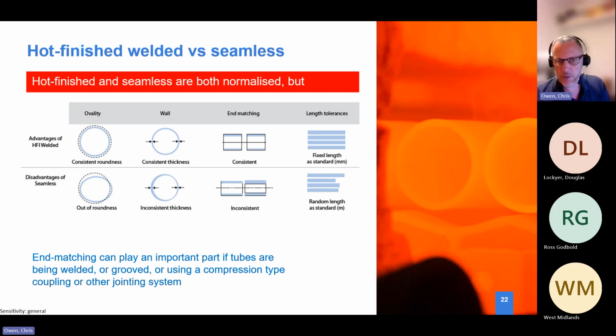And when we talk a bit later about corrosion issues and installation issues, it's worth noting that sometimes if you have seamless tube which has different end matchings, when they're welded together or joined together, there could actually be some steps internally, and that could act as an initiation point for corrosion or a place where debris can collect. So again, we will always try and promote the advantages of a welded tube because of that consistency and the tighter tolerances we are able to achieve. Then it means when you actually join tubes together, you don't end up with that change in geometry, which can cause some problems, which we'll talk about later.